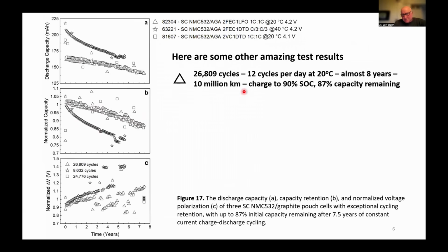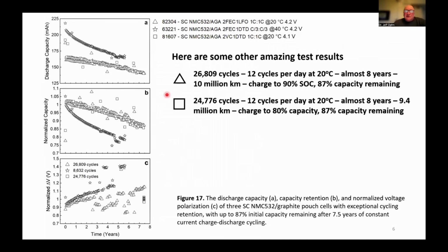And this cell was charged to 90% state of charge every time, 12 cycles per day at room temperature. So just being hammered, and it would have driven a vehicle 10 million kilometers and still have 87% remaining. And the square data is very similar to the triangle data. This one is only charging to 80% capacity, but it shows almost identical behavior. Again, almost 8 years of testing continuously, 9.4 million kilometers.